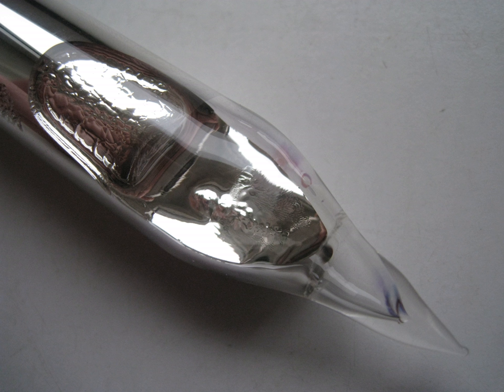Rubidium silver iodide has the highest room temperature conductivity of any known ionic crystal, a property exploited in thin film batteries and other applications. Rubidium forms a number of oxides when exposed to air, including rubidium monoxide and rubidium oxide. Rubidium in excess oxygen gives the superoxide. Rubidium forms salts with halides, producing rubidium fluoride, rubidium chloride, rubidium bromide, and rubidium iodide.